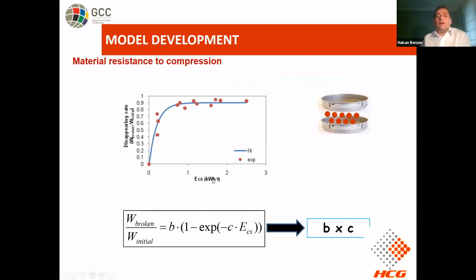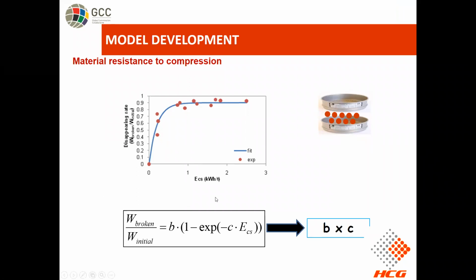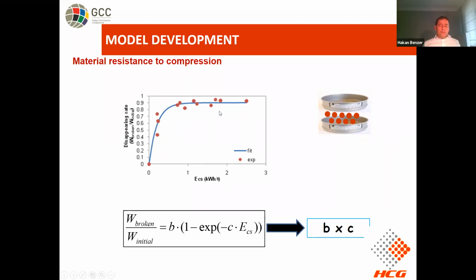Again, it comes from our characterization technique. This is the material, we call it material resistance to compression, or in other words, during the operation, we measure the disappearing rate of the top size particle under piston and die. So at varying energy levels, we measure the disappearing rate. Then according to the equation, we calculate B multiplied by C, which is the material softness. And this goes well with our model structure.